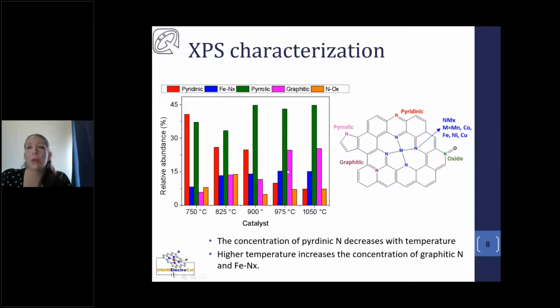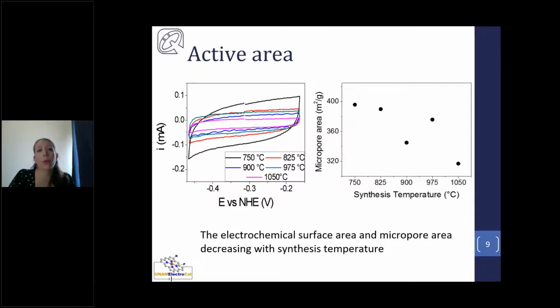If we look with XPS to the concentration of different nitrogen functionalities, we clearly see that the concentration of pyridinic nitrogen, for example, decreases with synthesis temperature. By contrast, the concentration of graphitic nitrogen and nitrogen coordinated to iron increases with synthesis temperature. So we can see that the possible active sites are changing with the synthesis temperature. In addition, when we look at the active area of this material, we see that it's also changing with the synthesis temperature. In particular, we see that a higher synthesis temperature leads to a decrease in active surface area, which is a negative thing for catalysis.